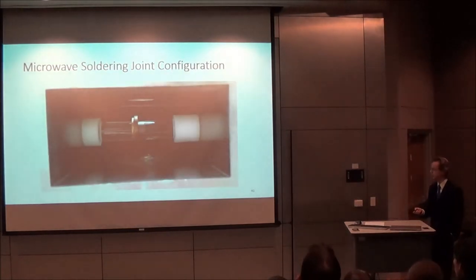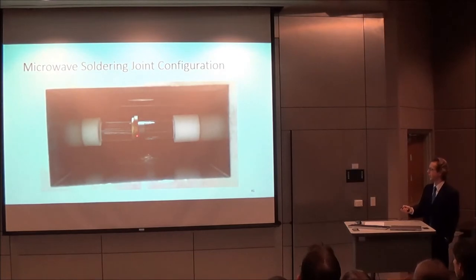And so this is the configuration of how the joint would sit in the waveguide, placed in the pressure fixture with the ferrite susceptor next to the copper base material, as the metal is going to be very thermally conductive.